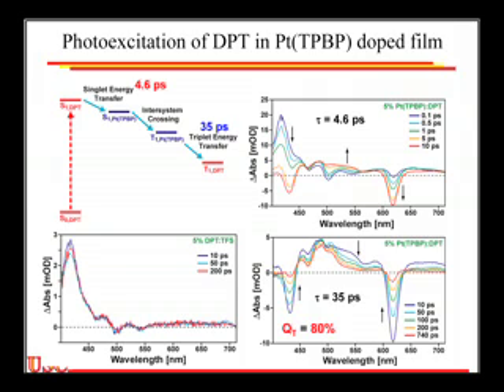This peak here is actually excited state absorption. This has a very high S1 to S2 absorption coefficient. So this is actually excited state absorption that dominates the bleach. So we don't see a bleach in this case. But we can watch the decay of the absorption, and you can see the singlet. This is a singlet absorption. The singlet absorption decays. It goes down at the same time the bleach shows up in my Squaraines and Q.